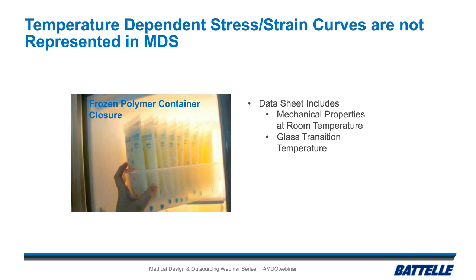So the data sheet includes the room temperature. It also includes the glass transition temperature, and you've looked that up too, so you're confident that the material is not going to become brittle at your freezer temperature. It's still going to be rubbery because you're above the glass transition temperature. But what you don't anticipate is that stress-strain curve also shifting and the modulus getting higher, that elongation at break getting lower. So you're missing out on tensile properties at freezer conditions. So here maybe you've designed for one elongation, but that was at room temperature. Now you're in a freezer, and when that material, the fluid inside the bag, freezes and expands, it could cause it to go past that yield point at the freezer temperature and cause a rupture. So that's what we're trying to avoid here.